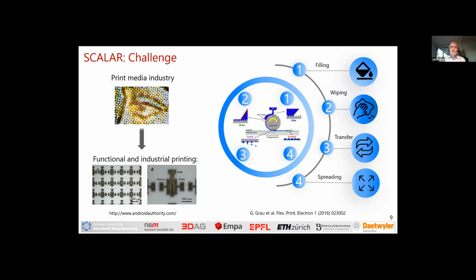Each of these processes has certain requirements or can be optimized for an ink. One of the findings of the group of Subramanian and the work of Gerd Grau was, if you take one characteristic of ink in the printing process, the capillary number, which contains surface tension, viscosity, but also printing speed, then for each of these capillary numbers, you will see that one of these 4 processes is the limiting process, so the ink transfer process. So the big challenge in this project is how do you optimize what kind of ink and what kind of printing conditions you need to optimize all these 4 processes involved at once.